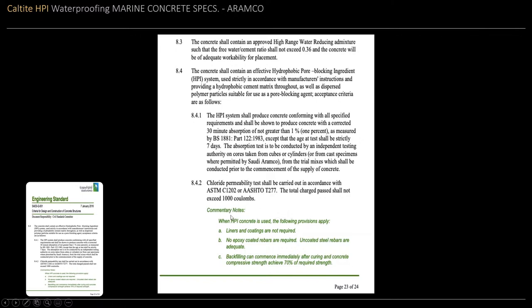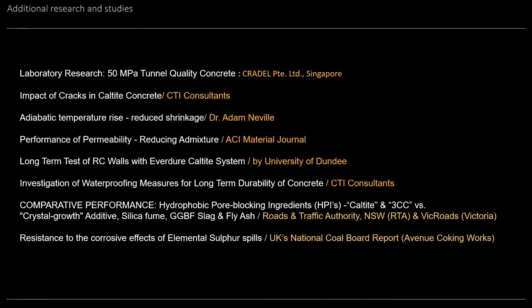What's interesting, the commentary notes at the bottom here, when HPI concrete is used, the following provisions apply. Liners and coatings are not required. No membranes, no coatings. No epoxy-coated rebars are required. Uncoated steel bars are adequate. And things that contractors love, backfilling can commence immediately after curing the concrete, and the compressive strength is achieved 70% of the desired strength. So that can save an awful long amount of time during construction.